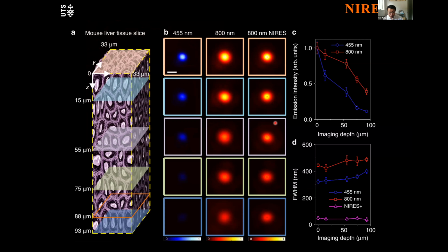So over here is basically the single nanoparticle. And the amazing thing is once we increase for different thickness, we always can see this hole in the middle. And by just increasing the power a little, for this depth almost like 80 milliwatt or something, you still can see clearly the single nanoparticle here. So the PSF, the resolution of this image, is still maintained at 50 nanometer.